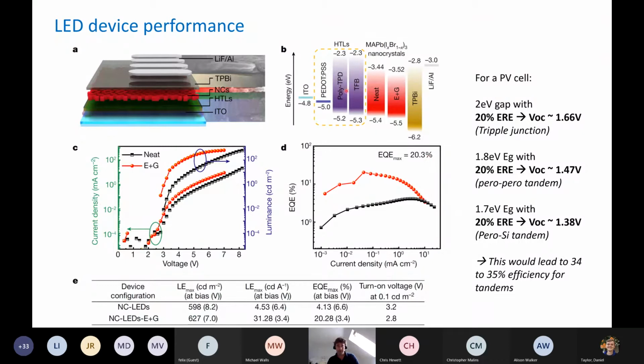Now, this is not a structure that would work very well as a solar cell, but it indicates that these materials, when interfaced with semiconductors that are similar to charge extraction layers in solar cells, can deliver very high radiative efficiency. Just as an example, if our solar cell had a 20% radiative efficiency with the bandgap we need for perovskite on silicon, then we'd have a 1.38 volt VOC from that wide bandgap perovskite cell, not just 1.2 volts. And in fact, that would lead to a 34 to 35% efficient tandem cell.